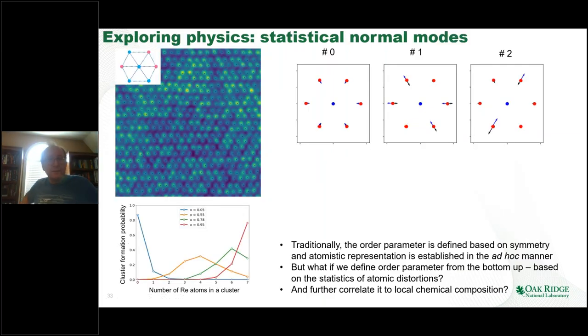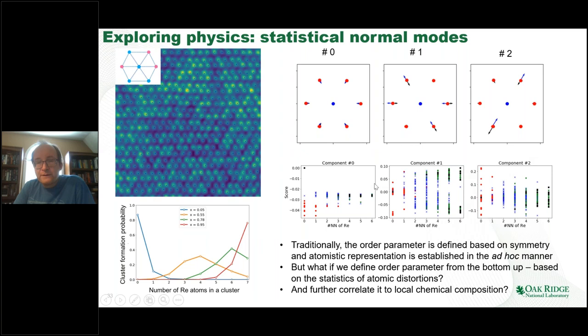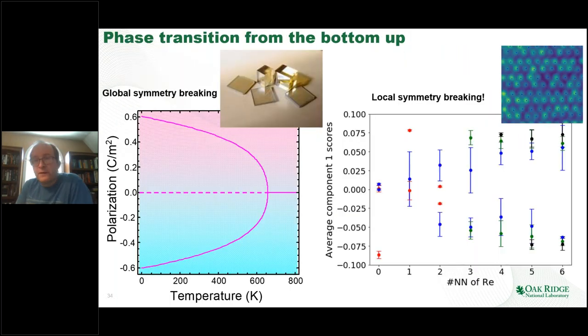I can also make the next step, which is that I can measure the distortions of the lattice around each atom and start to analyze these distortion patterns as a function of the local chemical composition. So macroscopically, we have only four compositions, but locally we have fluctuations of concentration. And we can see how the symmetry breaking happens at the level of one atom. If we go through all the mathematics, which is not particularly difficult but tedious, we can see that the symmetry breaking happens when we have between one and two rhenium neighbors.